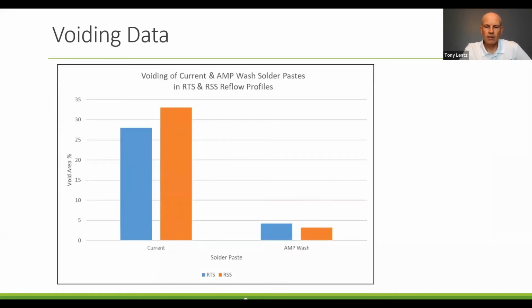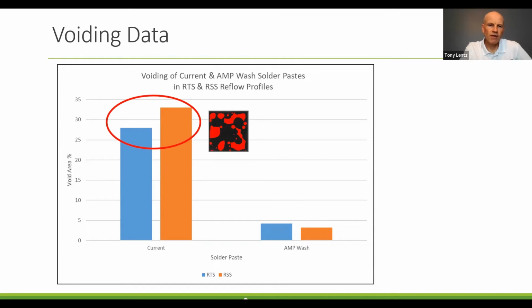Here's the big kicker with amp wash. This is the main thing it was designed to do. It was designed to reduce voiding levels from the current solder paste here on the left, which had void areas ranging from, say, 25 to 35% roughly in both ramp to spike profiles and ramp soak spike profiles.